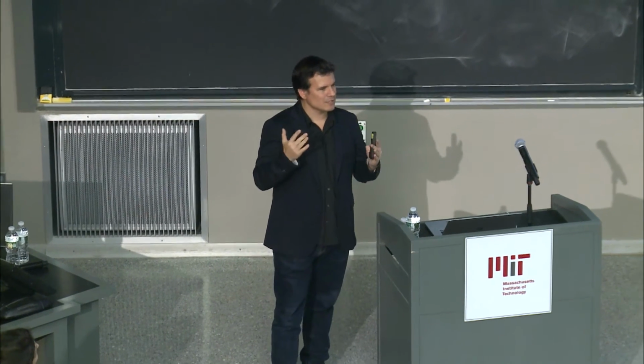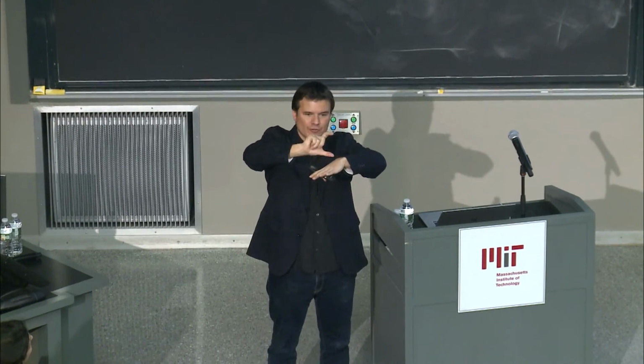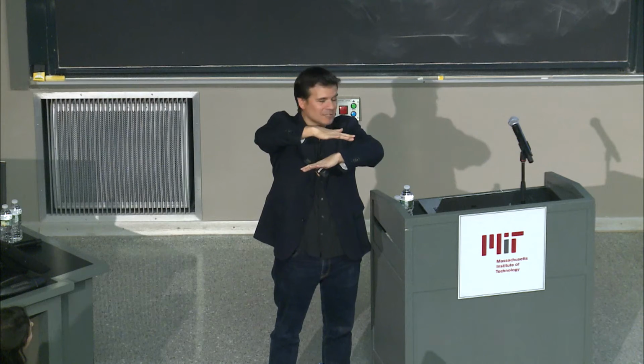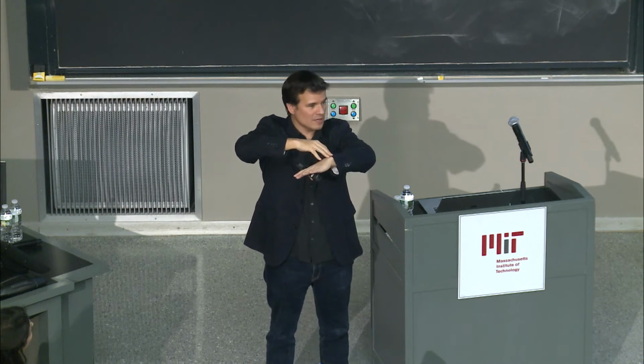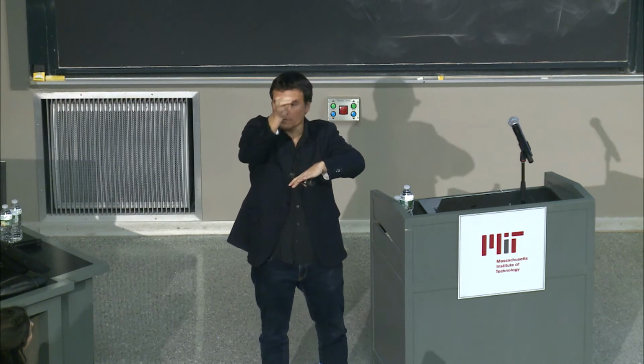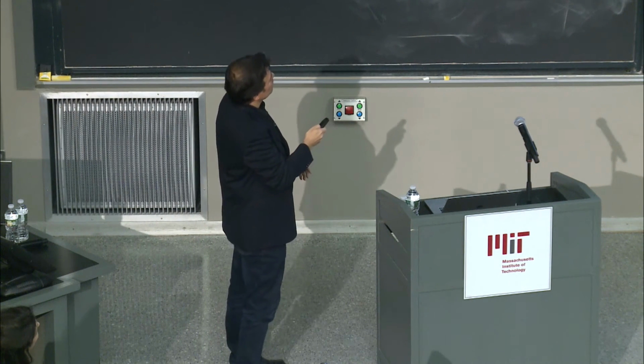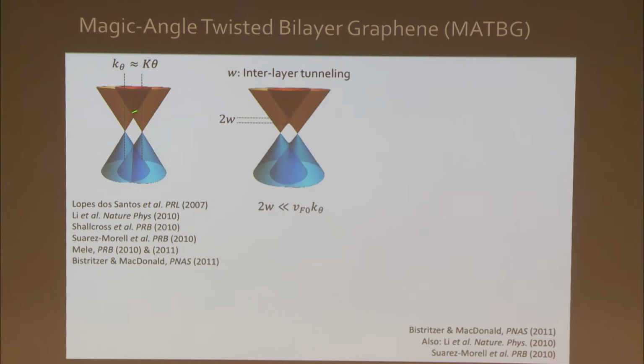However, when we place these two graphene sheets on top of each other, they're only 3 angstroms apart. So the electrons are very much aware that the other graphene sheet exists, and in particular, they can tunnel between the two sheets, back and forth. Okay? That leads to band repulsion, or a gap, an opening of a gap there at the crossing point. That is the same thing as bonding and anti-bonding states in the hydrogen molecule, but now for a giant graphene molecule. Now, the situation shown here is when this interlayer tunneling is much smaller than the energy of that crossing point. But what happens if I now keep reducing and reducing the twist angle?